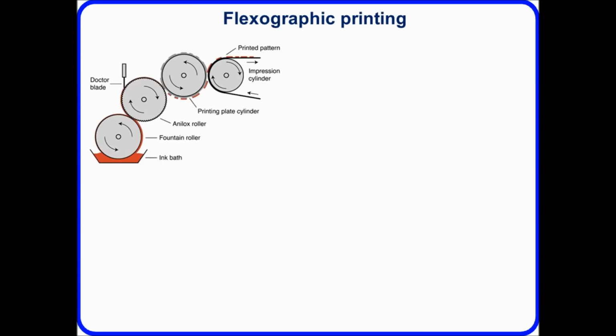And then another technique we use is flexographic printing. So I mentioned we have another set of rheology requirements, but here we have an ink bath, and we transfer graphene ink onto a roller, which then transfers onto an anilox, which has a blade which can then transfer the ink onto a printing plate. So we have our design on a rubber stamp on this cylinder, and then we have our flexible substrate on another roller where the ink will transfer from one to the other and leave behind a pattern. So this is the technique you would use to print newspaper. So it's a very fast process, and we were able to print graphene inks up to around 30 meters per minute.